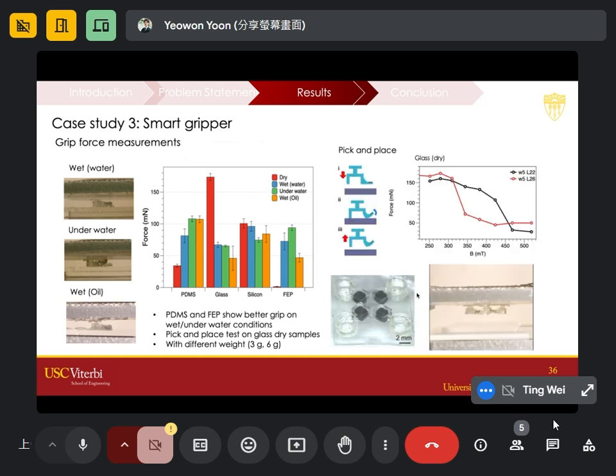So this is a pick and place test we did with the single gripper on different lengths of the bin. And these are the arrays of the gripper that we printed. And this is the video. It shows it gripping something, and then after some point it loses the grip when the magnet approaches. So it lifts up. This is about 60 millinewton. And then the cantilever is actuated, and therefore it loses the grip.